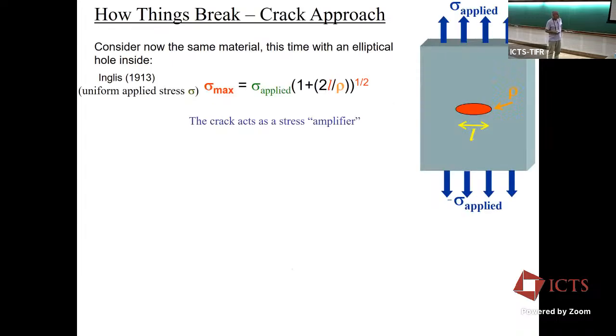And let's see why. The reason was given by Inglis in 1913, when he took a 2-dimensional sheet of material. Again, I'll be ignoring for a while this 3rd dimension here. So we're looking at a 2-dimensional world. And he put an elliptical defect into the material, and then calculated what the stresses are. The applied stress here is totally uniform. What are the stresses at the tips of the long axis of the ellipse? And this is what he found. The stress was amplified by this factor: 2 times the length of this ellipse divided by the curvature at its tip, to the power of 1/2.